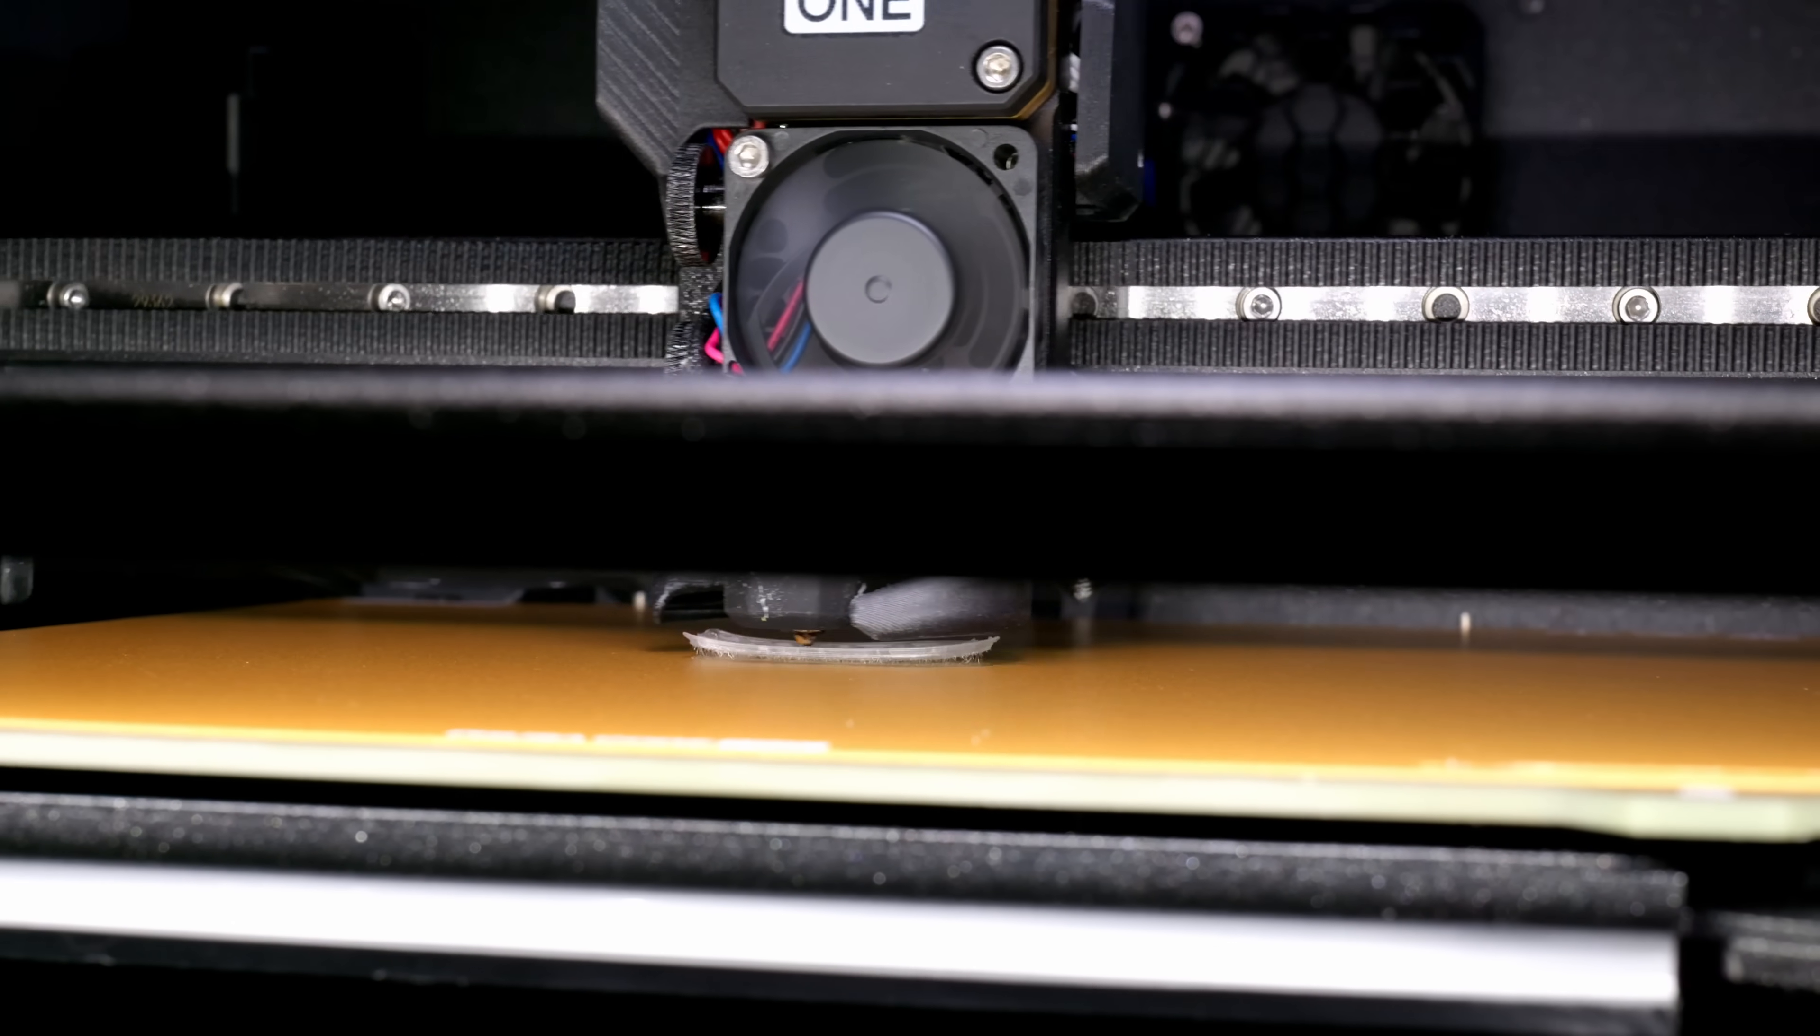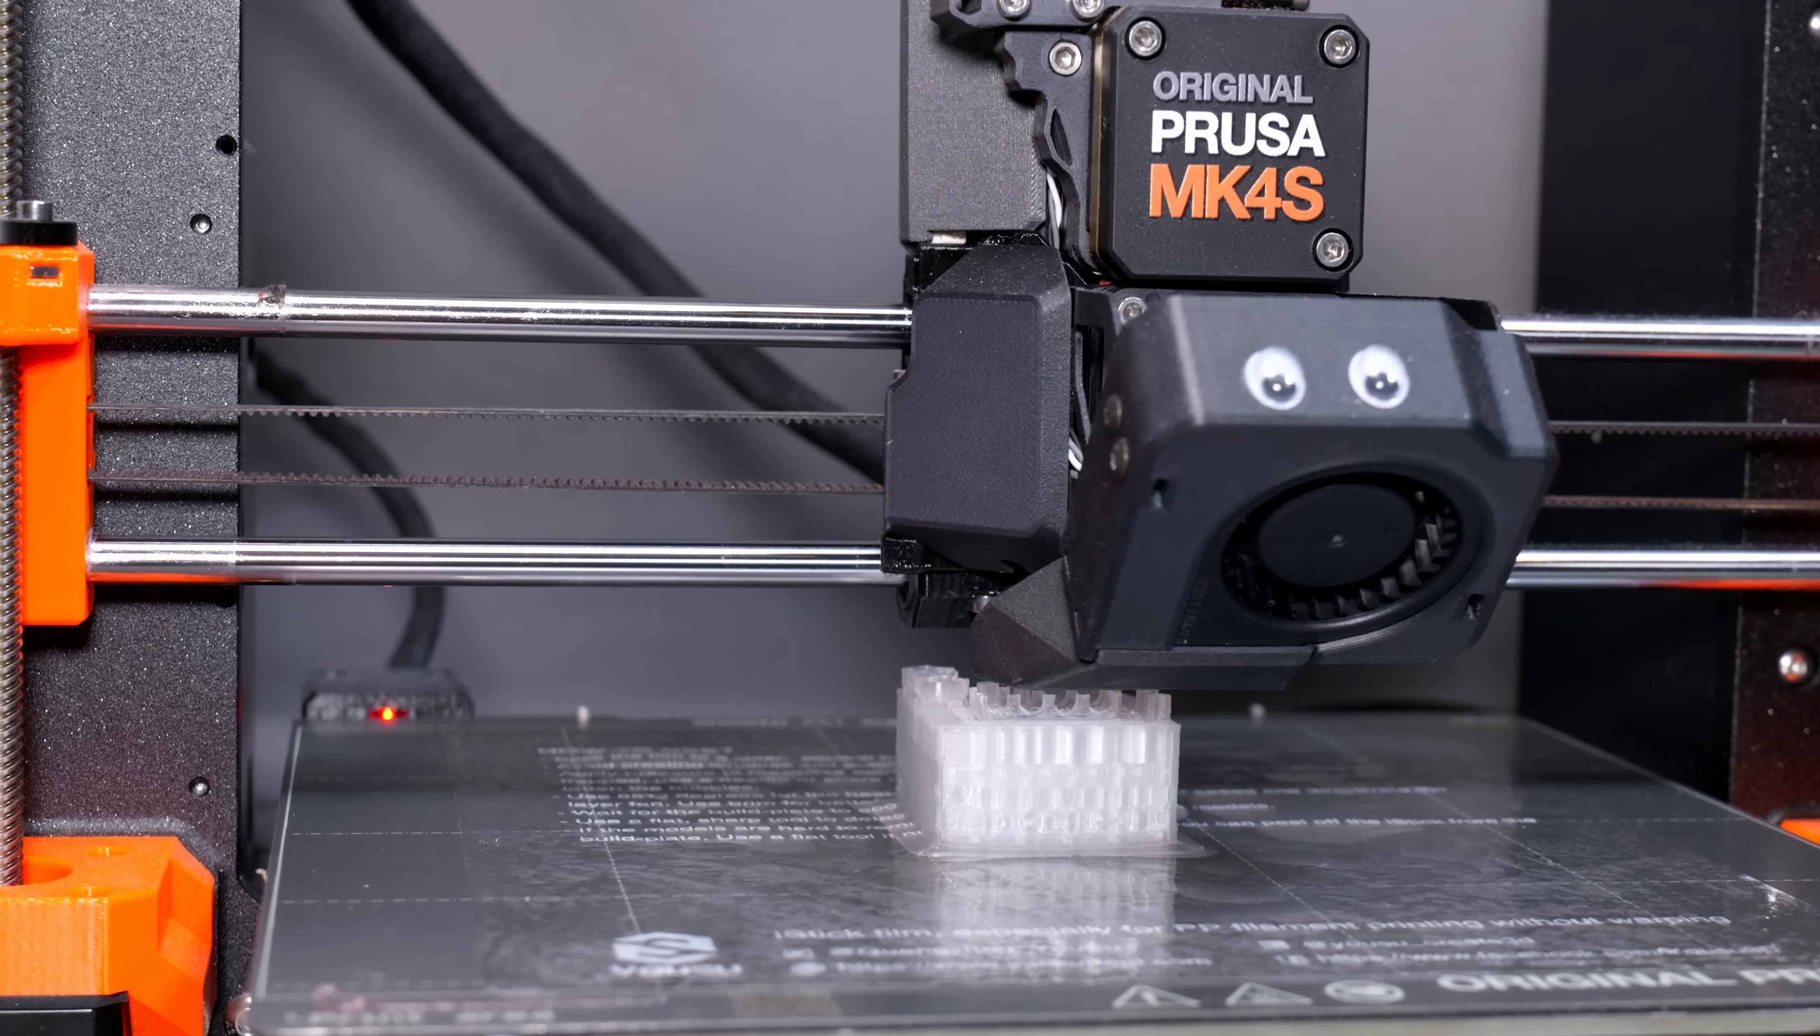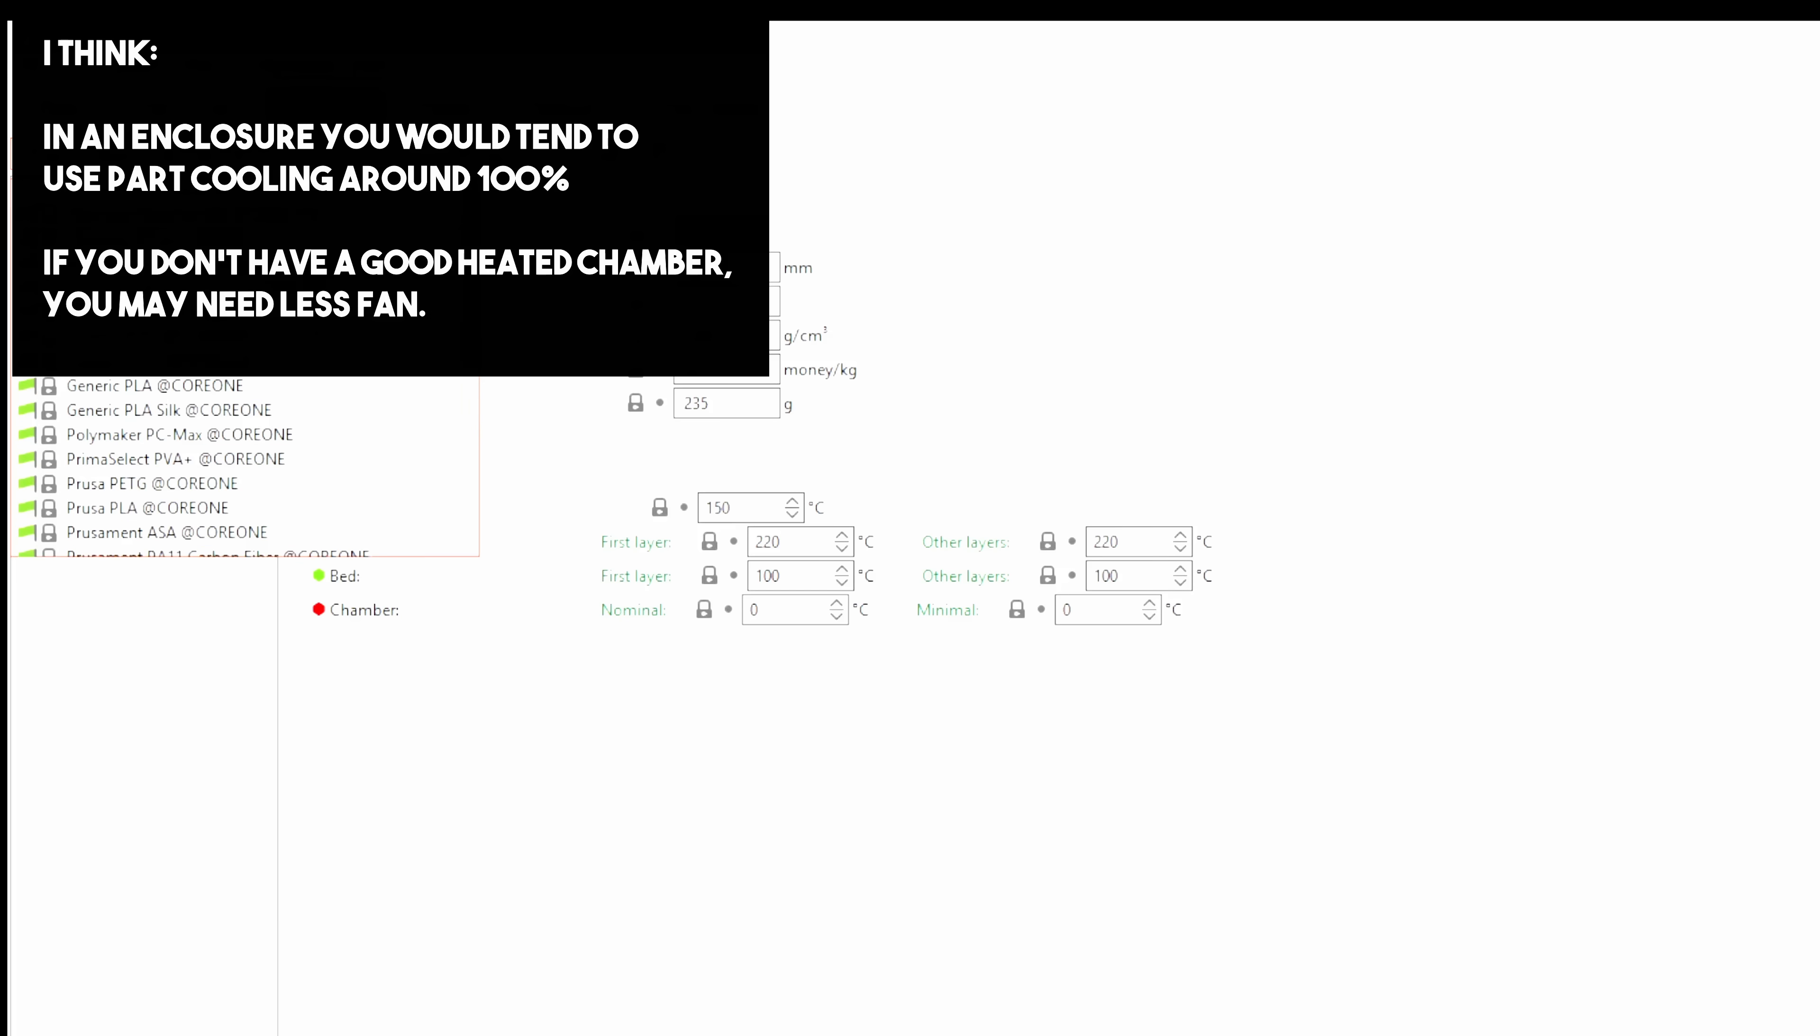But we need to come back to that because when I tried the Prusa polypropylene sheet I was actually initially confused because it just didn't work at all. But it turns out there was a reason for this. To print polypropylene you need a fairly normal nozzle temperature, not that different to PLA or PETG, but what you do need is you need a very high bed temperature, like a minimum of 90 degrees C. This isn't so much because you need the temperature to make the polypropylene stick, it will probably stick to a cold bed, it's just more that you're trying to stop it warping. An enclosure I think is not 100% necessary in the same way as ABS because I haven't seen it cracking further up the print and you do actually use normal fan speeds, but I think an enclosure will definitely help from the perspective of shrinking away from the bed so it's not a bad idea.